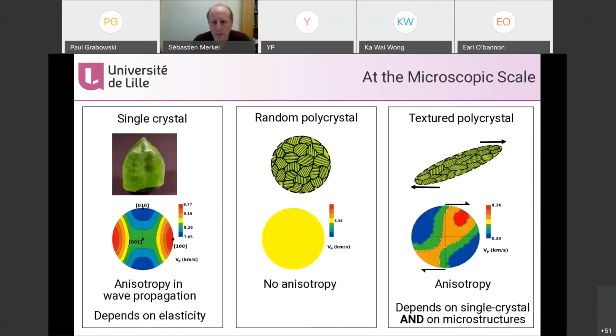Now, if you look at the microscopic scale, why do we have anisotropy of propagation of waves? It's because minerals are anisotropic in terms of elasticity. You'll get anisotropy in the wave propagation depending on their elastic properties, and most minerals are anisotropic. But if they are randomly aligned in a polycrystal, then you won't get any form of anisotropy. On the other hand, if you have a texture, if you have lattice preferred orientation, then you'll get anisotropy again. And the anisotropy you get depends on the single crystal properties, on the elastic constants, but also on the microstructures.